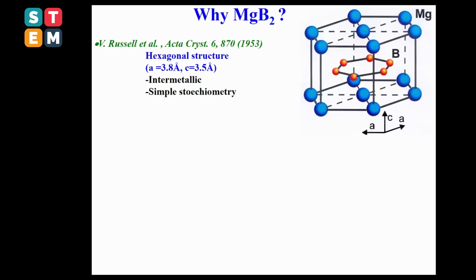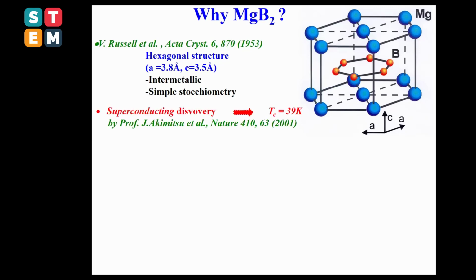1953. The stoichiometry seems to be quite simple, hexagonal structure. But the superconductivity was discovered in this system in 2001, where the TC is 39K. Some advantages exist, as this material is quite strong mechanically. You have low-cost materials and also low density, seemingly light materials.